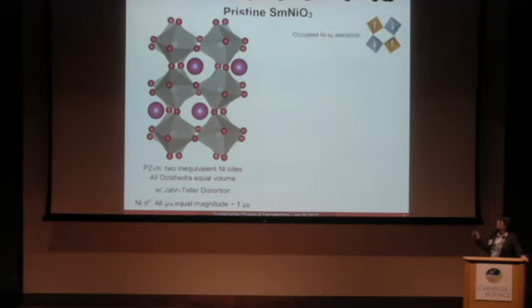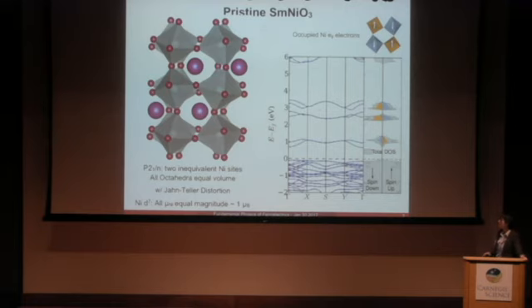So representing my unit cell with 4 nickels in a slightly cartoon-ish scheme, I'm going to be showing also the occupied nickel eg electrons. So in the d7 configuration, you have 1 eg electron. Here this is showing the 2 different sublattices of the nickel, and they each have 1 eg electron in the pristine state. In the accompanying electronic structure, we see a small gap, and this is occurring between the eg states of the nickel. We do see a very large hybridization with the oxygen states. Here I've colored in the remaining unoccupied nickel eg states. And so we see that for each sublattice, you have 3 times 2 remaining eg states, and the remaining gray density of states you see around it is the part attributed to the oxygen.